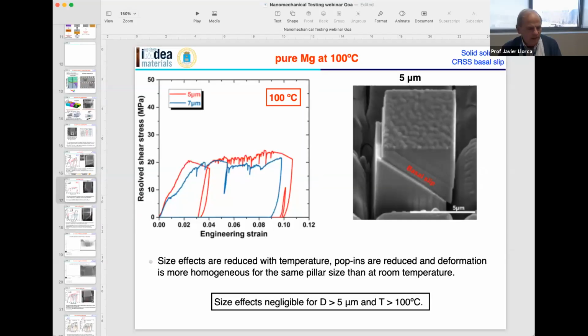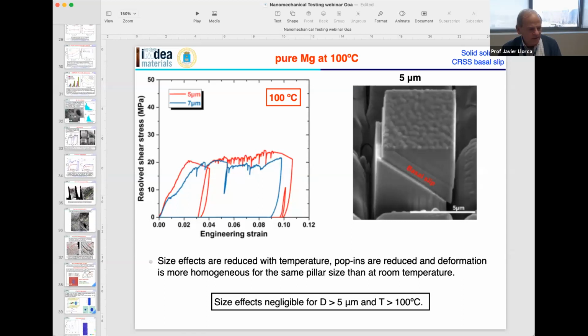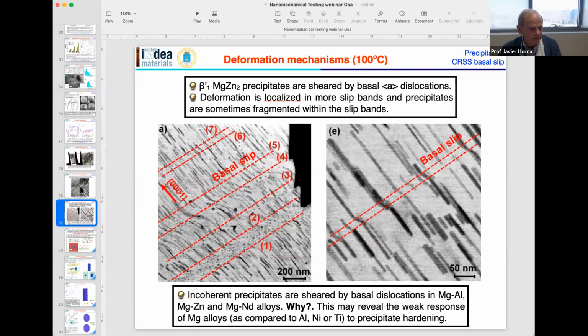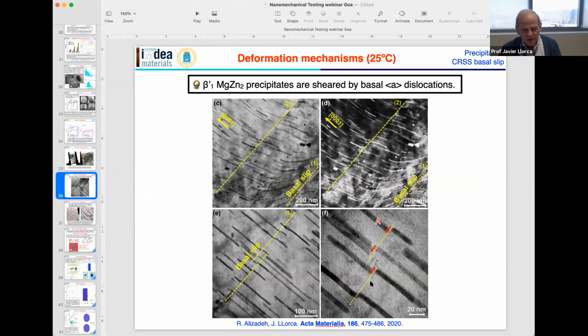Yeah, so that's some new discovery. These results are recent, published just last year, and there is more evidence coming up. The standard knowledge is that with coherent precipitates, dislocations in the matrix can go into the precipitate because they share the slip plane, and that's true. But then, I'm going to share the screen again, we did this mechanical test. When you do this mechanical test, you can see that the dislocations are shearing the precipitates.